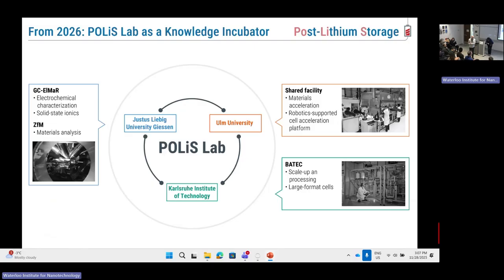I think the best assumption we have today is that the lithium primarily goes into grain boundaries of the copper, that there is really a solid solution coming up. I know there are some papers coming up recently. I don't think that the bulk solubility of lithium in copper is 20%. It's more, I would say, a grain boundary solubility. The diffusion is rather slow. So we estimated, in the case of our current collector, which was a few, let's say 10 micron, that it will take a few years to saturate it with lithium. So it may be part of the issues.